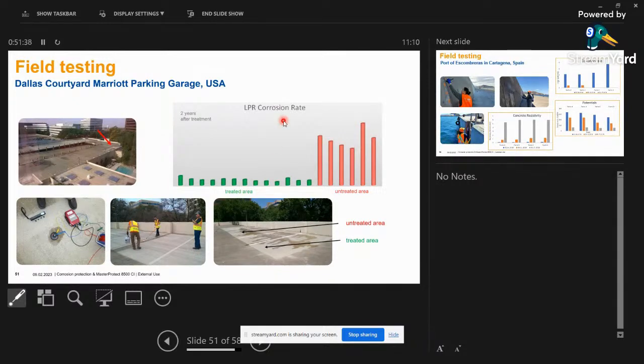As you see here, these are the untreated areas, so clearly the corrosion activity is very high, and you see 2 years after treatment, still you don't see the corrosion activity happening. So you can see treated and untreated areas lying side by side, and how effective this simple liquid is to inhibit the process of corrosion is clearly observed. You can observe it very clearly here as a direct measurement of the corrosion current.